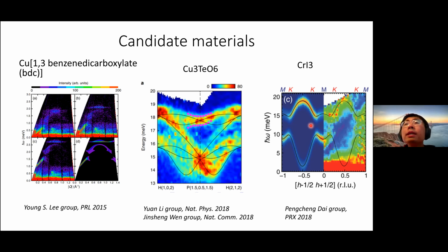More recently, for the two-dimensional magnet chromium triiodide, in the ferromagnetic phase, people have also used inelastic neutron scattering to suggest that each of these magnon bands, the lower band and the higher band, have non-trivial topology in the sense that a quantity known as the Chern number is non-zero for these two bands. So they suggest some edge state will happen, a chiral edge state between these two bands. These are the leading materials for topological magnons.